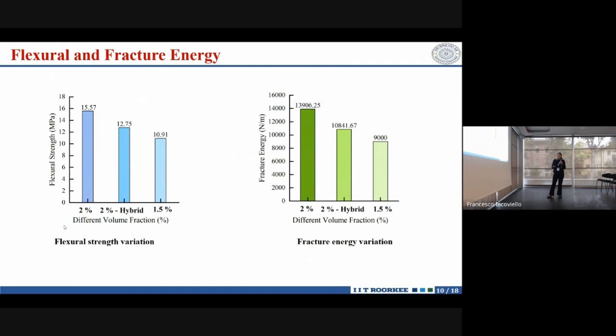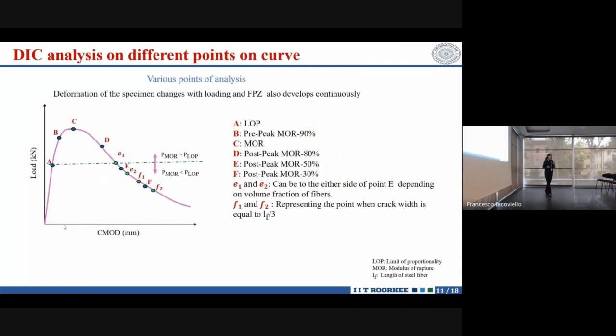But to get the details of the crack and everything, as we see the results of DIC, we will be able to comment on the mechanism that is happening behind. So to do that, we have used the DIC results. And as we know, the deformation changes with the specimen as the loading progresses, and the fracture process zone is continuously developing. So in order to observe the appearance and the propagation of the fracture process zone, we have divided the pre- and post-peak profile into different segments.